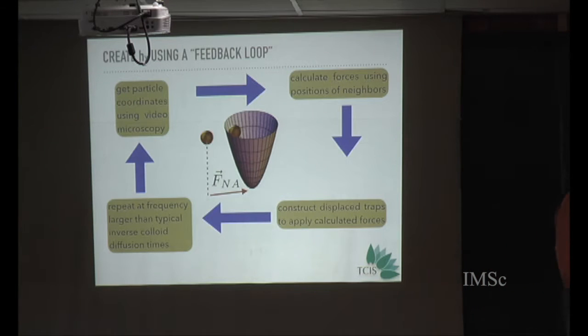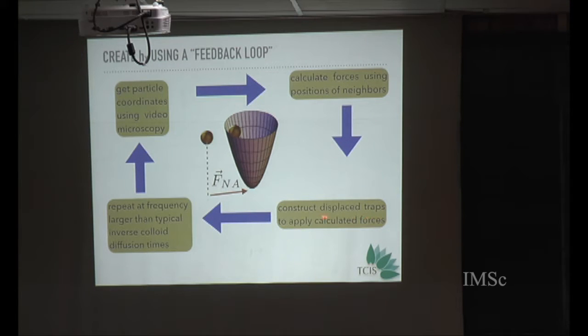But it turns out that you can actually generate this field in the lab. And this is something that we are talking about with colloid experimentalists. And the idea is this. Nowadays it's very simple to get particle coordinates using video microscopy in a colloid. So you get these particle coordinates. You can calculate forces. This you do in a computer, so it can be done very fast. And then you have a set of laser traps. And you can construct displaced laser traps to apply exactly the force that you want. And you can repeat this at a frequency which I am told is 600 hertz, which is much faster than any time scale of motion of a standard colloidal particle.